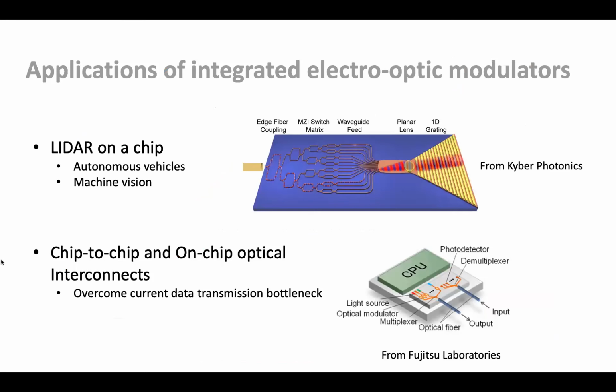If you build a device like this, you can make a lot of interesting things. For example, this is so-called LiDAR on a chip. What you do here is beam steering. You send light in through the waveguides, then you judiciously choose the phase shifts and recombine them, and it allows you to steer. That can be used in a car which drives itself, so it can avoid your favorite dog. You can also make chip-to-chip communications. Barium titanate works really well at 1.55 microns, so it can talk to fiber directly.